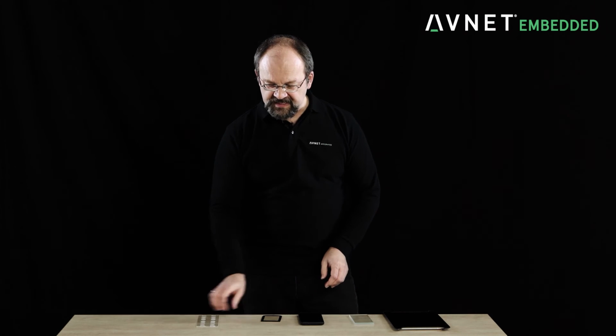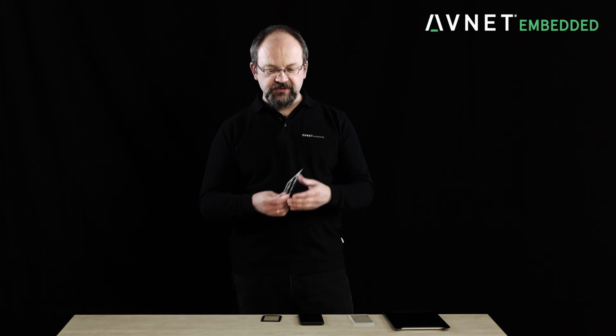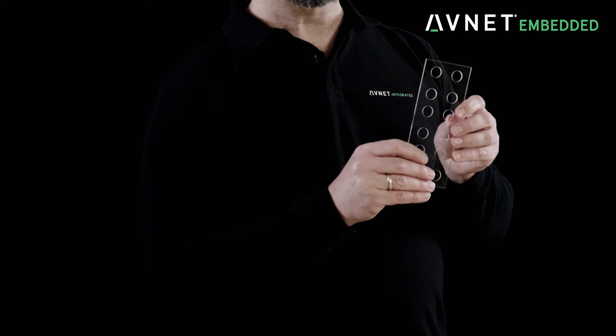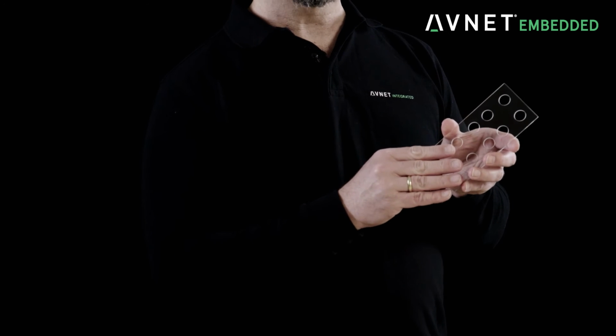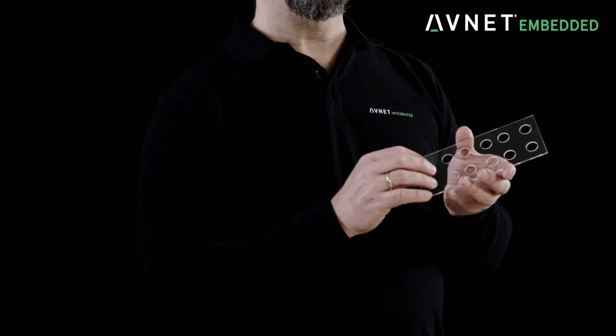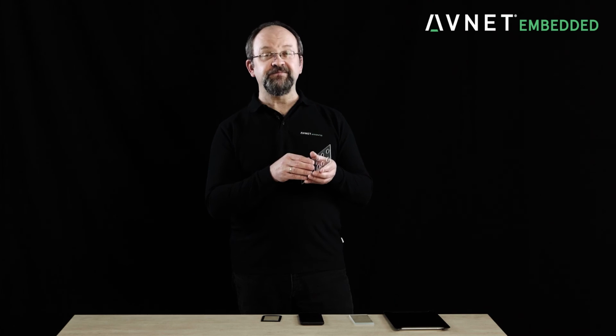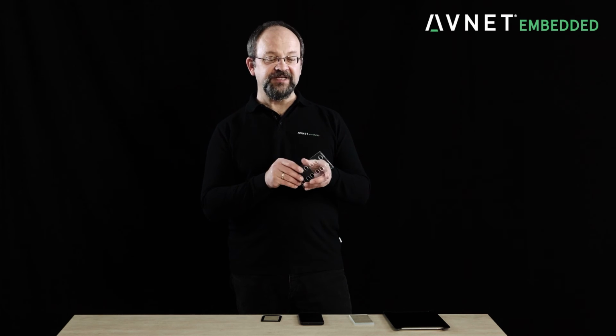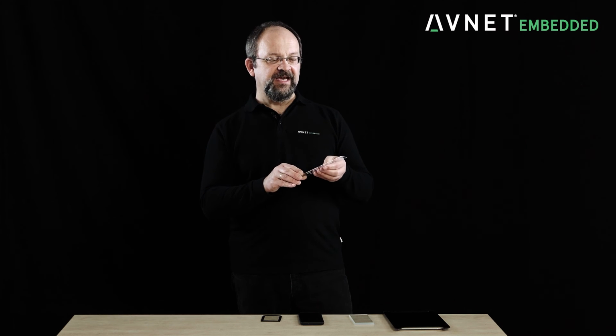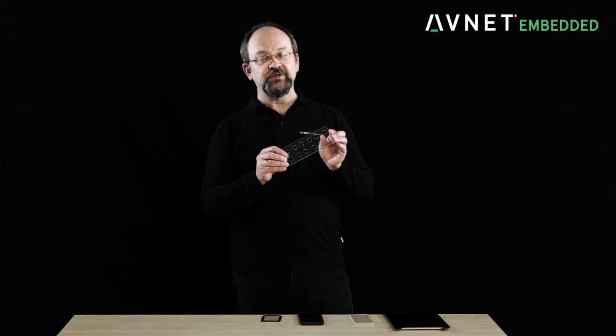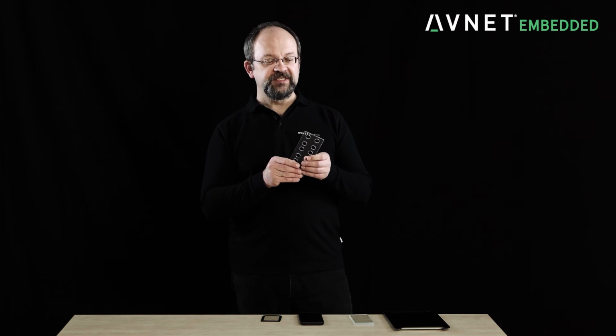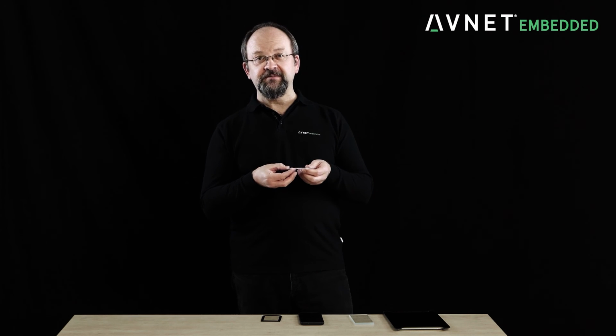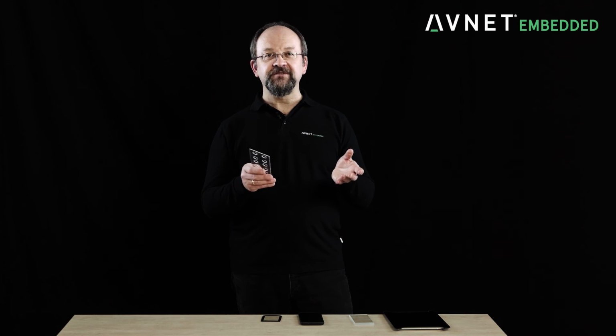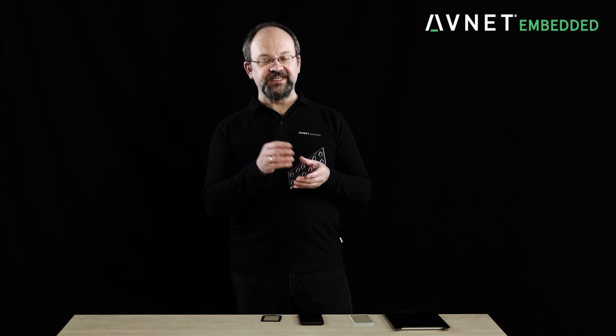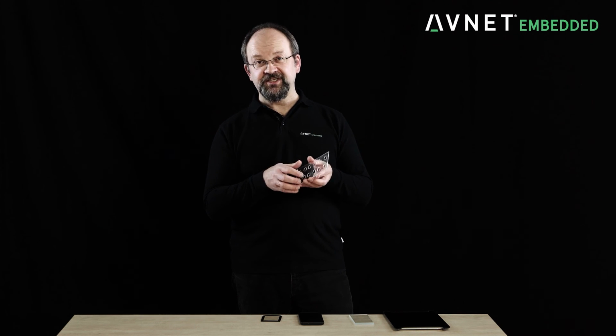The last glass I'd like to show you is so-called borosilicate glass. Borosilicate glass is used in ovens. It can take a lot of heat, about 500 degrees Celsius, and it can take a temperature shock of about 200 degrees between top and bottom. This borosilicate glass is normally not used in display applications, but it can be used, for example, in laboratories. It has a very high chemical resistance, and that may be a reason why you have it in front of a display, to protect it from chemicals which may splash against the front.